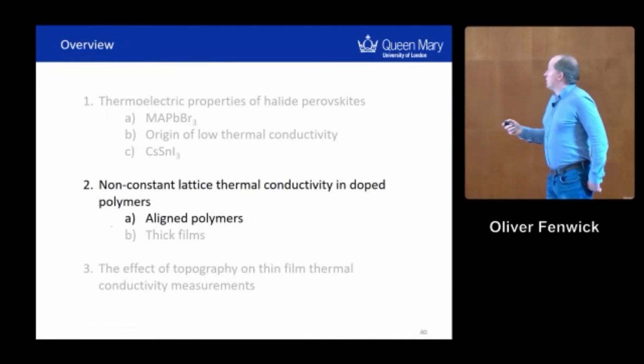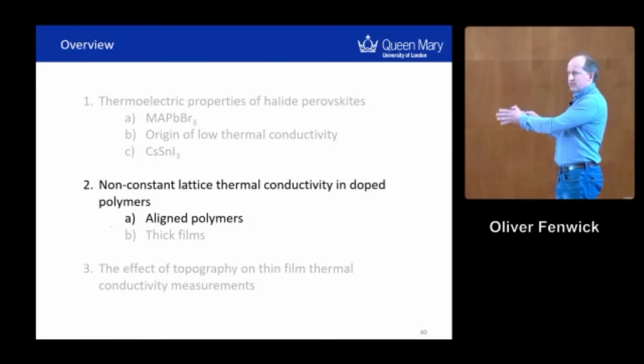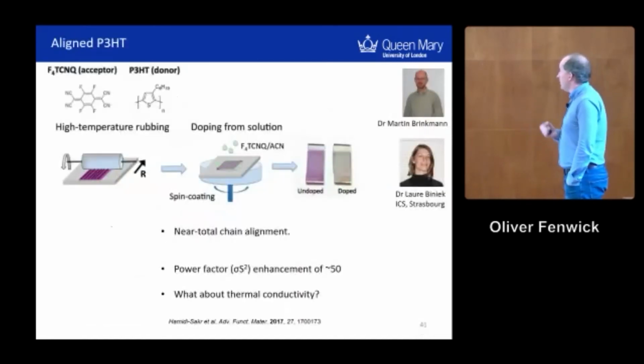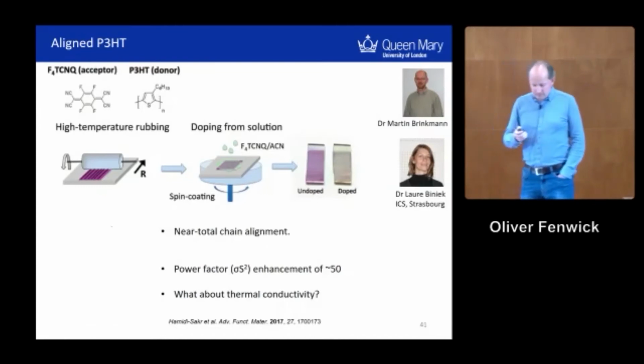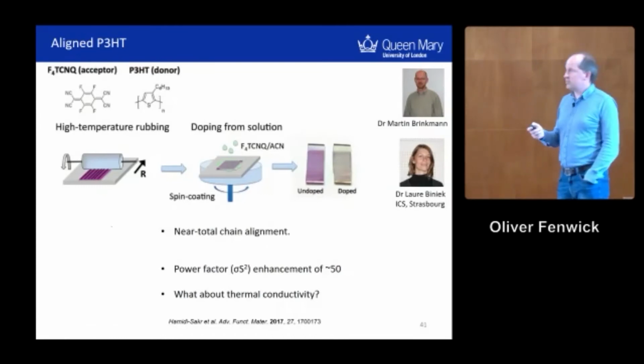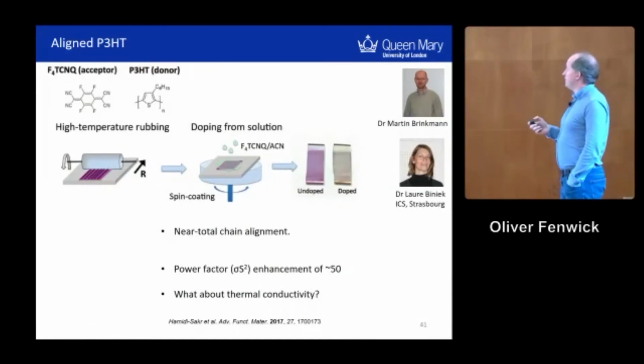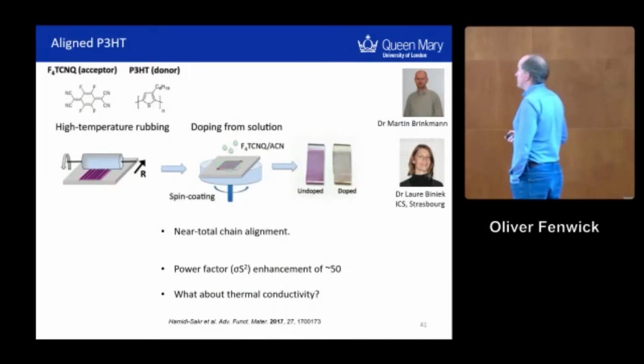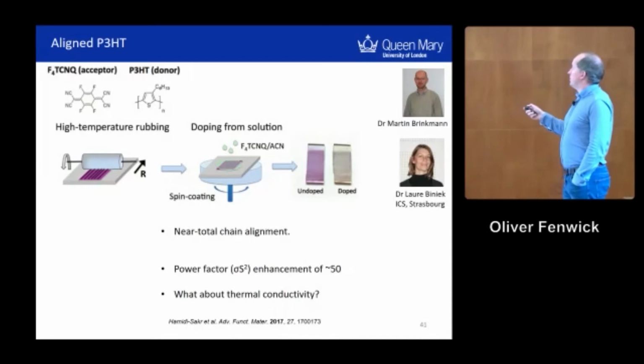Okay. So now I want to switch from those hybrid and not so hybrid materials to polymers, and specifically P3HT. And the first thing I want to look at is stuff that's been done in Strasbourg, so one node of this ITM. And this is the aligning of polymers for thermoelectrics. So they do this by mechanical rubbing of polymers using a very specially designed system they have in Strasbourg, and then doping them to make them electrically conductive. In this case, they used P3HT, then doped with F4TCNQ.